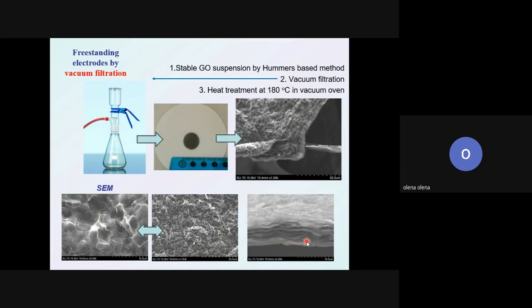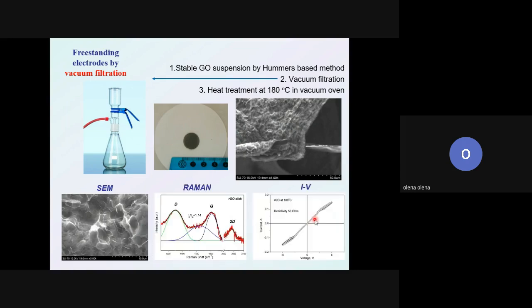Depending on the concentration of graphene oxide solution and the amount of solution, we can obtain different multi-layers. In my case, I know that I can obtain 5 multi-layers, but it can be up to, as you can see, I don't know, 50 or something like that. So we studied by Raman, calculated the ratio between the two peaks, and you see it's not high. It means that, of course, we have defects, but we have visible observations that we have reduced graphene oxide.